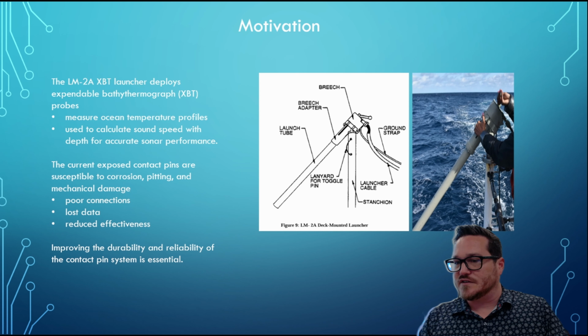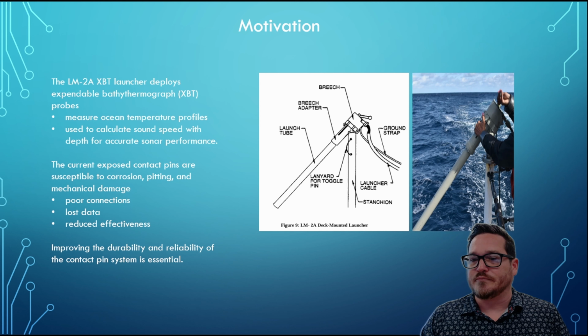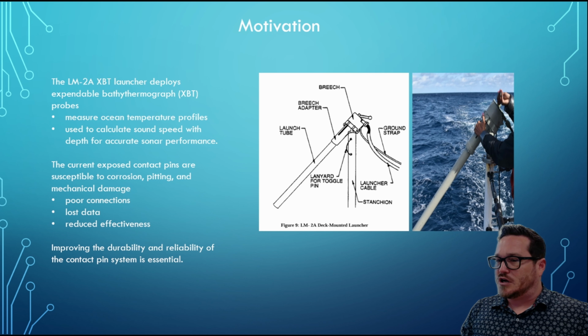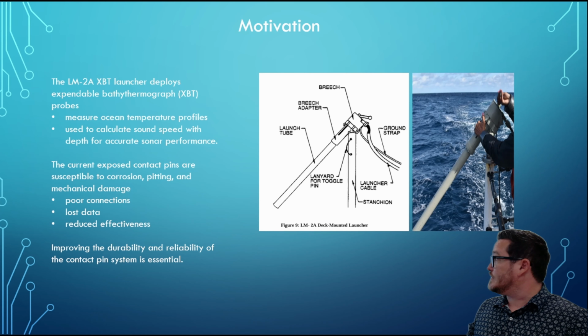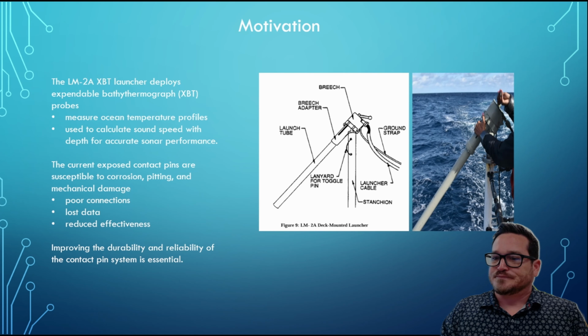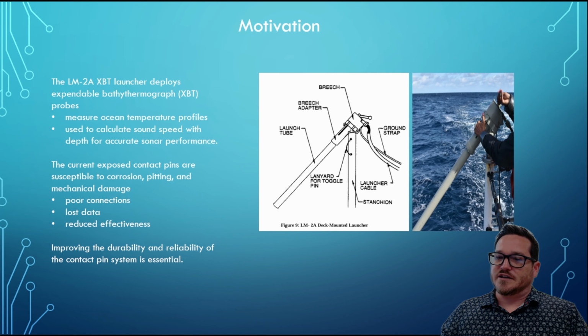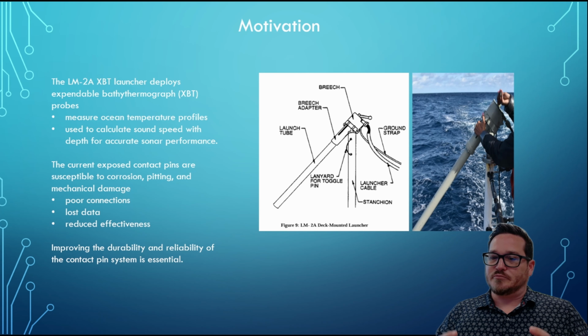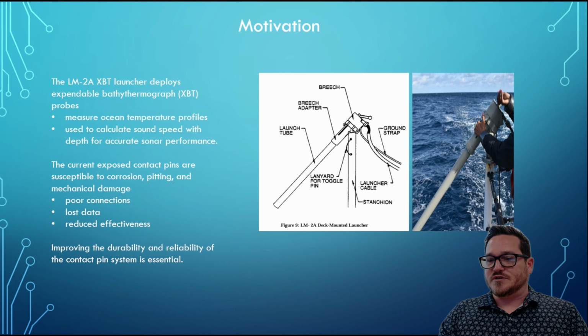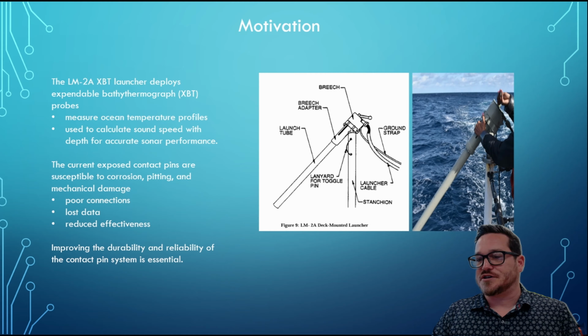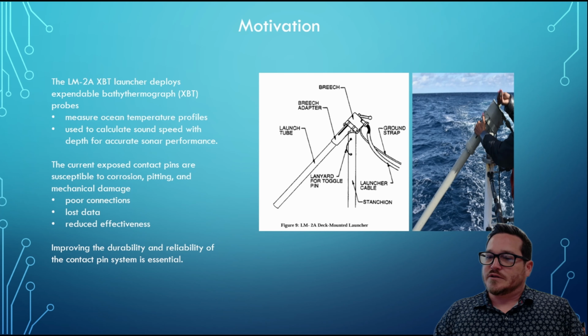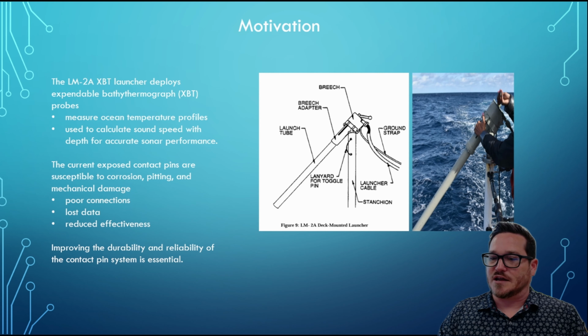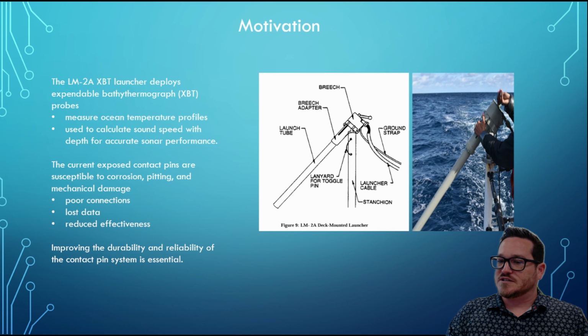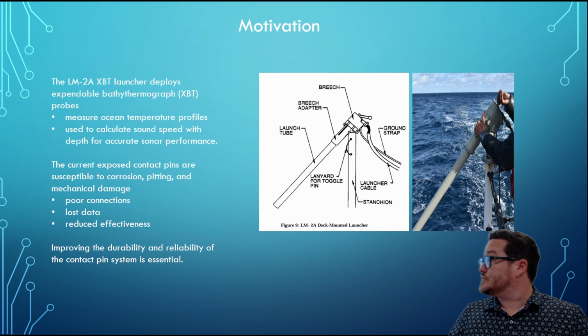For clarity, I have this drawing of the XBT launcher. During operation, the breech, or the launcher head, is opened by turning the lever clockwise that's on top of it, and then that allows the head to swivel to the right, opening up the breech itself. Then an XBT probe canister is loaded into the breech adapter. The launcher is then pushed back into place, and the lever is turned counterclockwise, pushing contact pins into the top of the canister.